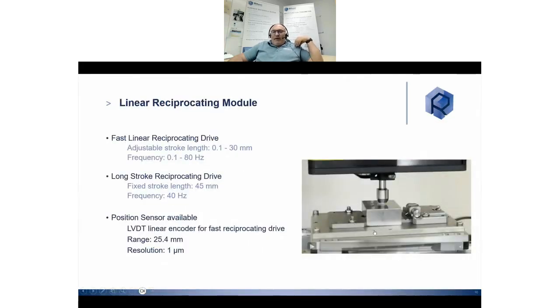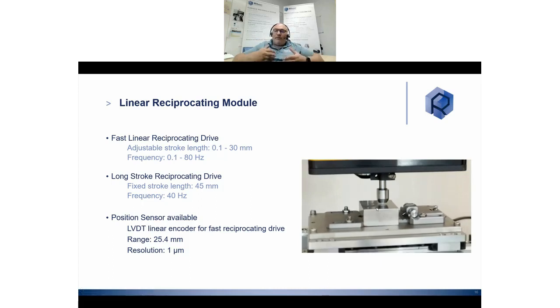We have a fast linear stage like here, and here we can choose in our software to change the frequency by step, maybe we start 1 minute at 2 hertz, 1 minute at 5 hertz, 1 minute at 10 hertz, 1 minute at 20 hertz. You can really change a lot. We go from 100 micron to 30 millimeter. We can go up to 80 hertz in frequency, and we have an LVDT encoder on the back to measure also the distance.